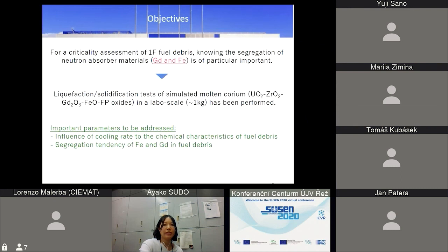So for criticality assessment of 1F debris, knowing the segregation of neutron absorber materials such as gadolinium and iron is particularly important. Gadolinium is important because gadolinium doped fuel is used in 1F reactors as a neutron absorber material. So gadolinium plays an important role for criticality assessment of fuel debris. And iron is also important because a large amount of iron is contained in fuel debris. So iron is also important for criticality assessment.